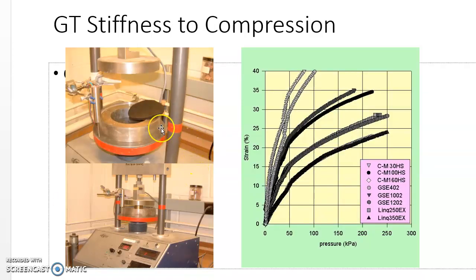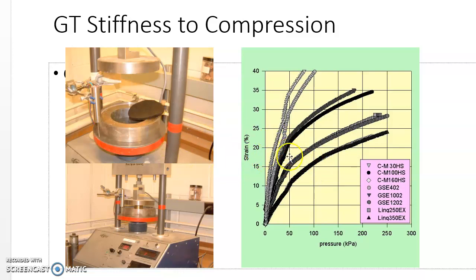I also tested the compressibility of needle-punch non-woven geotextile and compared the compressibility differentiated by the thickness of the needle-punch geotextile. From the test results, I noted that compressibility is higher for thin geotextile. I will explain how different compressibility impacts filter performance in the next slide.